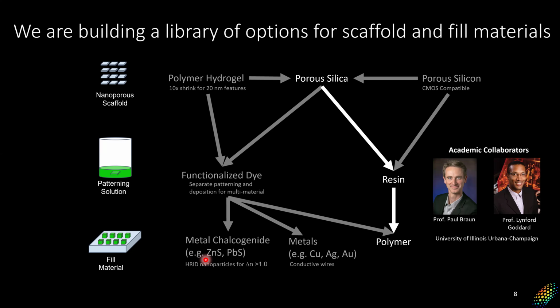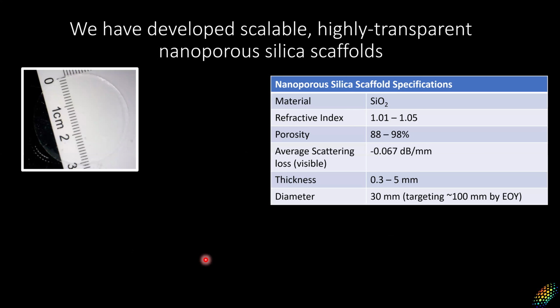Cool. So talking a bit more specifically about these highly transparent nanoporous scaffolds, we develop and make these in-house. This is an example of something we make currently. This is essentially a disc that's about 3 centimeters in diameter. We can control the thickness. Standard for us is about 1 mm thick, but we can go down to a few hundred microns and up to close to a centimeter, where you start running into issues with the working distance of the objective.